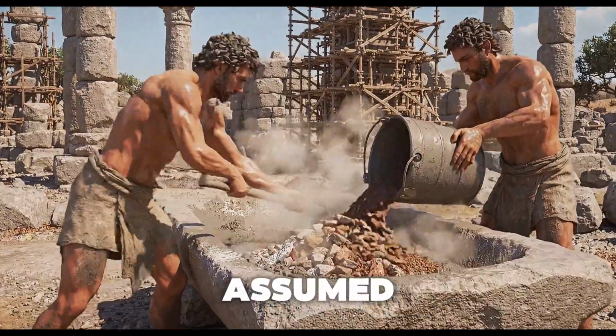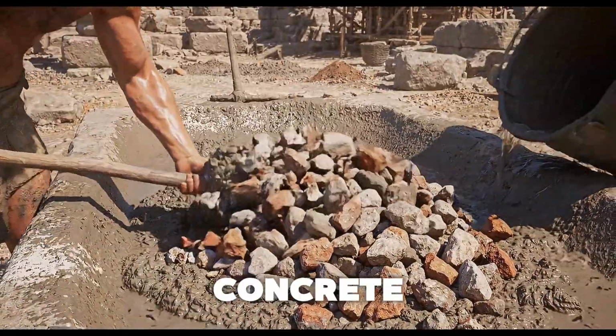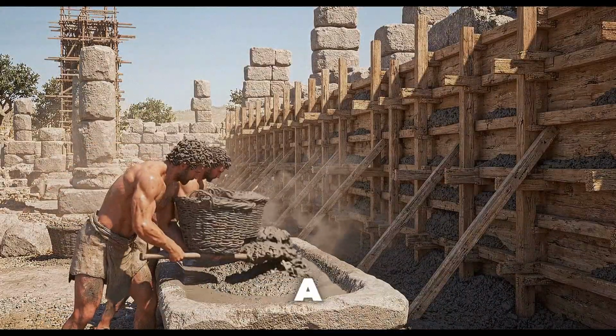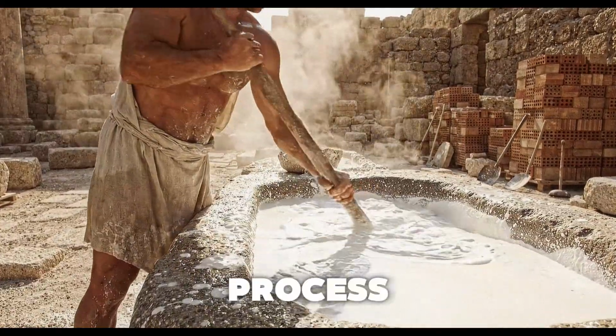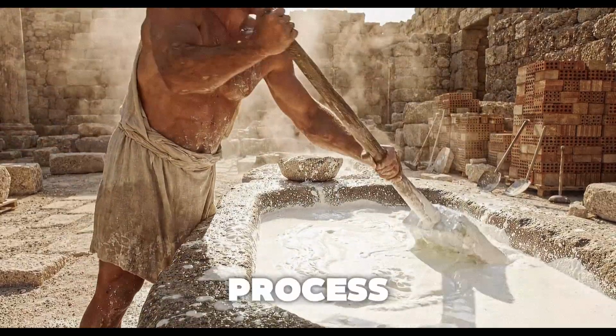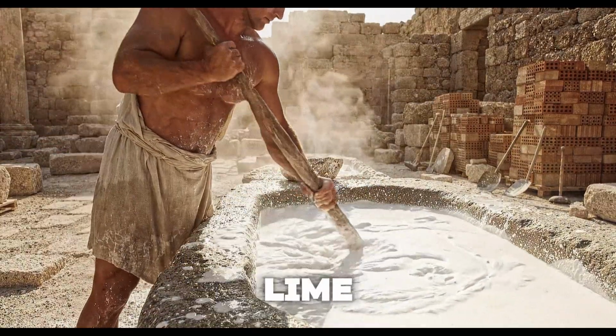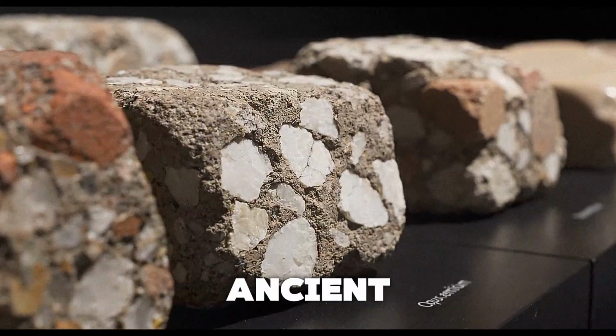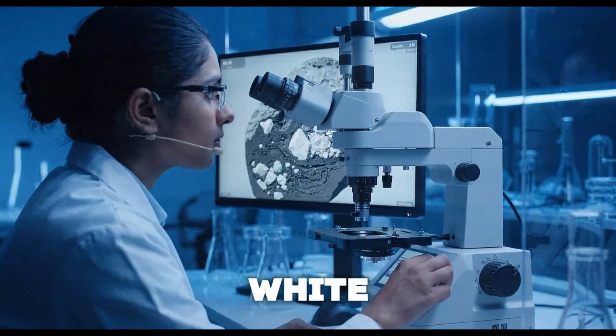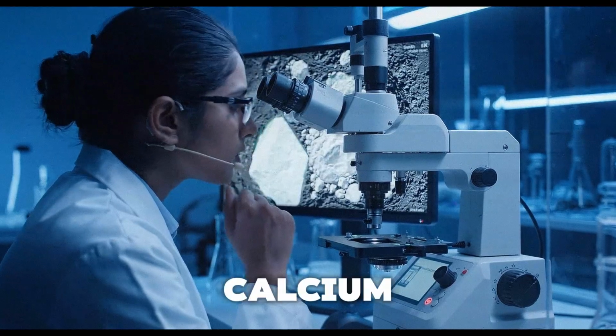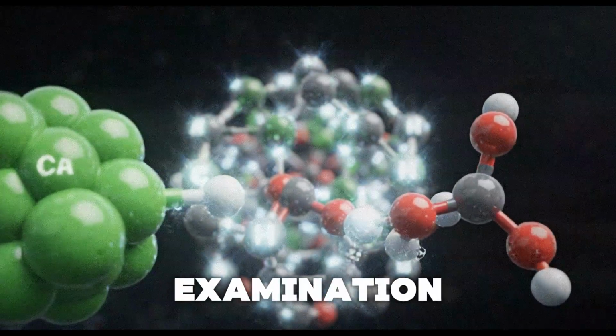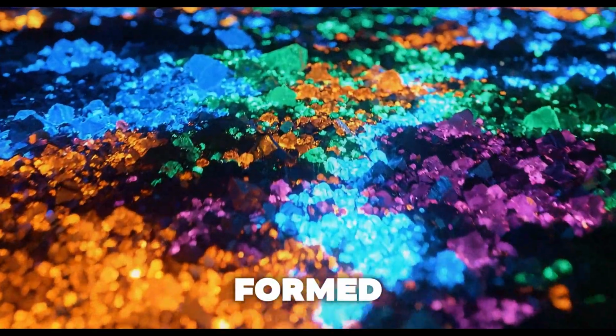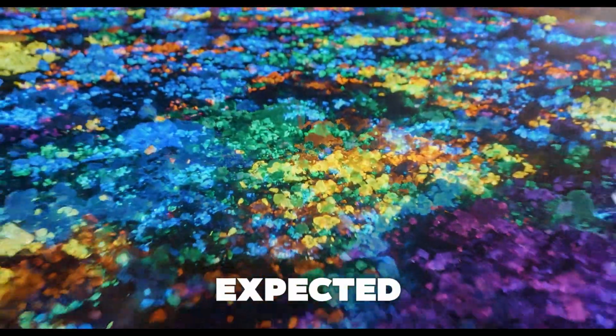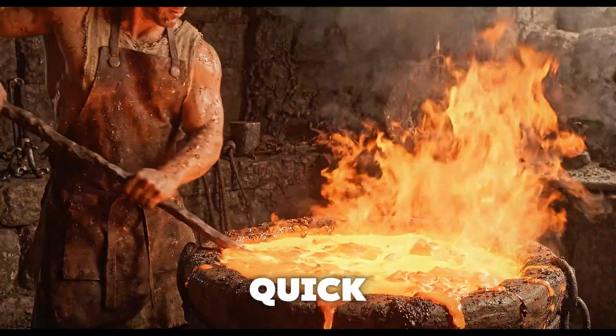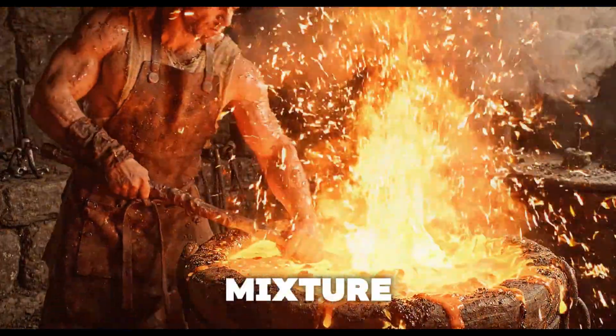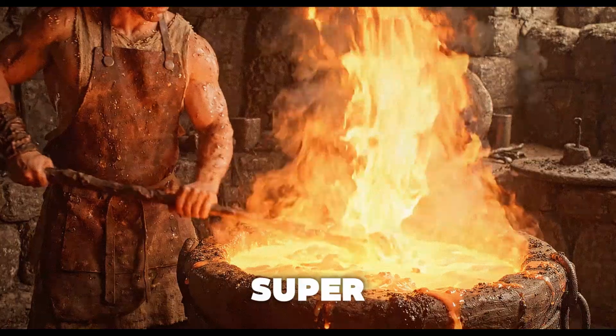Historically, it had been assumed that when lime was incorporated into Roman concrete, it was first combined with water to form a highly reactive paste-like material in a process known as slaking. But this process alone could not account for the presence of the limeclasts. Studying samples of this ancient concrete, researchers determined that the white inclusions were made out of various forms of calcium carbonate, and spectroscopic examination provided clues that these had been formed at extreme temperatures. As would be expected from the exothermic reaction produced by using quicklime instead of the slaked lime in the mixture, hot mixing was actually the key to the super durable nature.